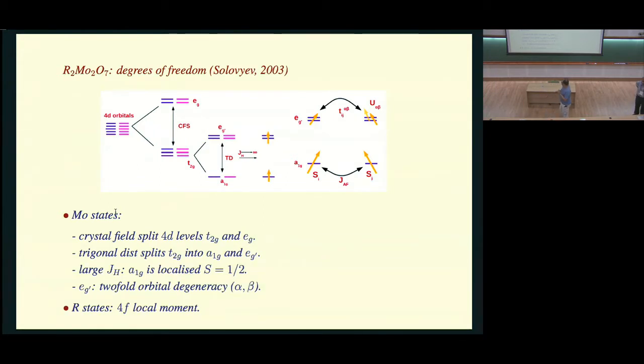What people have argued is not so much about polaron physics, but they point out that bond distortions, which have their origin in the electron-phonon coupling, are actually responsible for the freezing of the spin system from a liquid to a glassy phase. The fact that you get a 20 Kelvin spin glass temperature cannot be obtained, it's been computed by people, without significant bond distortions. Now, I am pretending that plays out only in the magnetic freezing sector and doesn't affect the electrons, which may or may not be true. But it seems that the major overall magnetic phase diagram doesn't seem to care too much about the electron-phonon coupling in the problem. The spin freezing does.